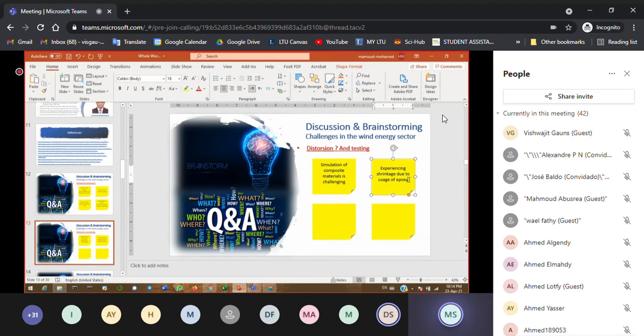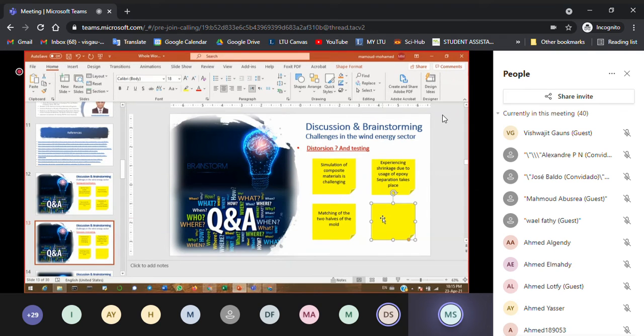But we did not actually do the model for that. But yes, we observed that. We were worried more about the matching of the two halves in terms of the mold itself, because in a 25-meter long blade, if you get 2-3 millimeters difference in each segment, in 15 segments, then you're talking about a 3-4-5 centimeter difference between the two halves. So yes, we experienced this kind of shrinkage, but we did not account for it in the design or the fabrication process.